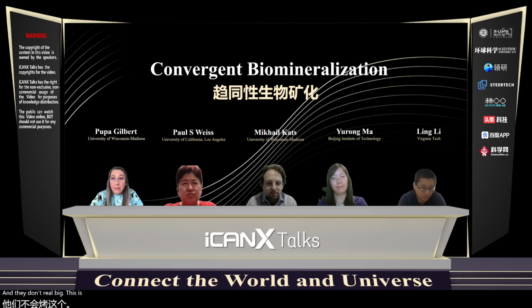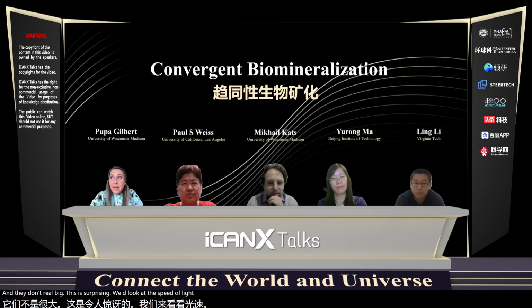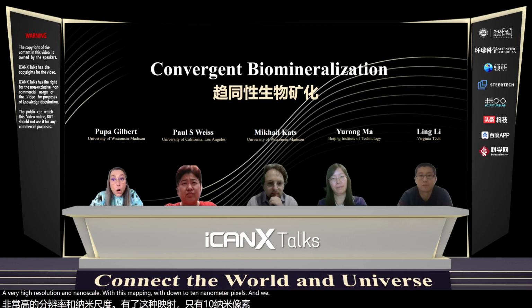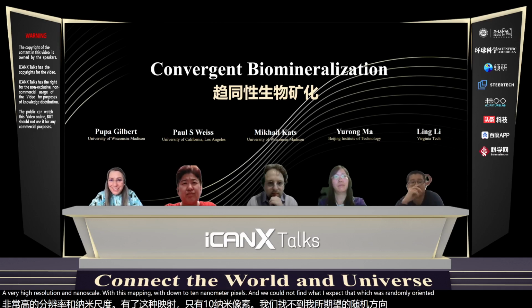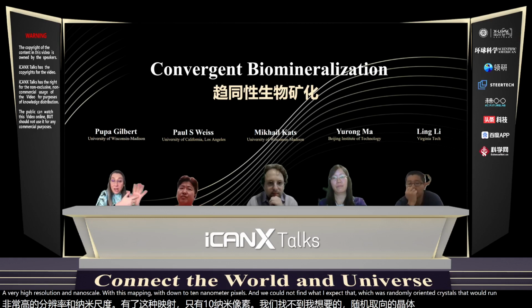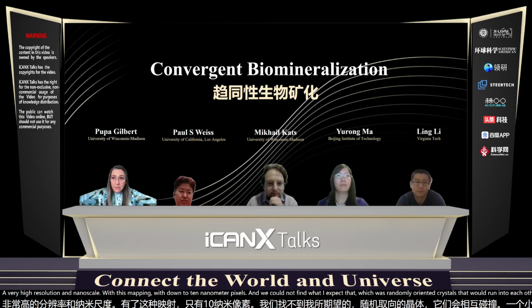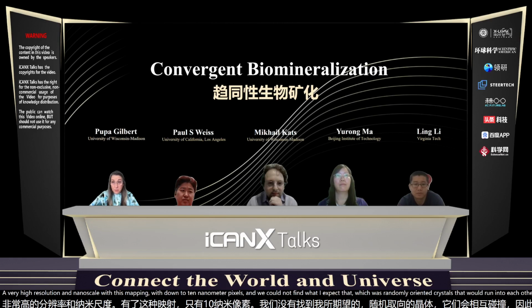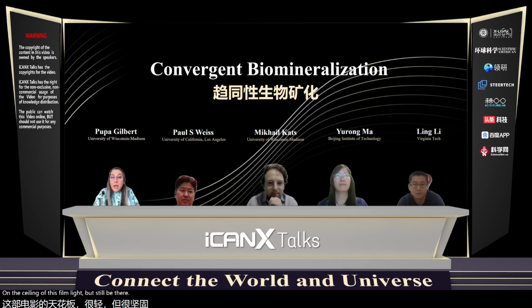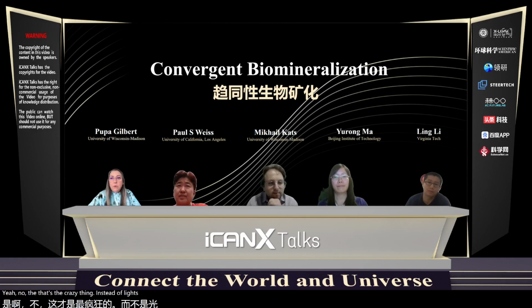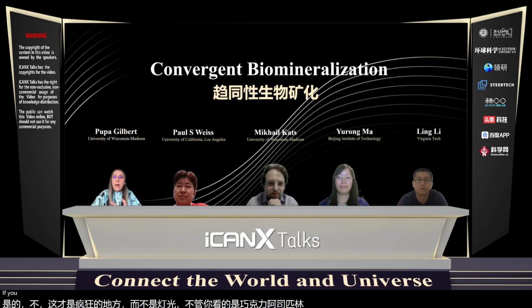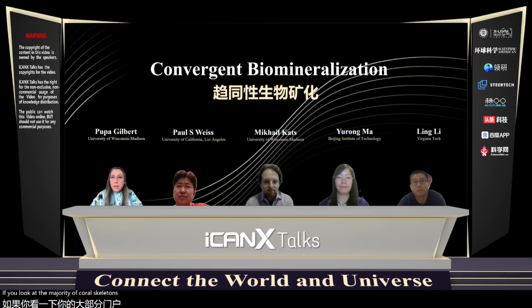This is surprising. We looked at spherulites at very high resolution and nanoscale with PIC mapping, down to 10 nanometer pixels, and we could not find what I expected, which was randomly oriented crystals that would run into each other, stay small, therefore not become the dominant component of the space filling of the spherulite, but still be there. They're not there. That's the crazy thing. In spherulites, whether you look at chocolate, aspirin, or the majority of coral skeletons, they're not there.